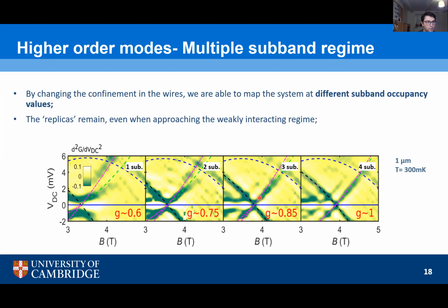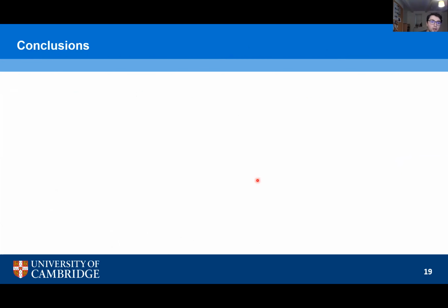And the reason for this is because you expect that once more subbands start being occupied, the 1D approximation could start breaking down. The fact that we don't observe this seems to suggest that each 1D subband is sort of independent of each other. They have very weak coupling between them. And as such, we can add multiple 1D systems sort of in parallel.